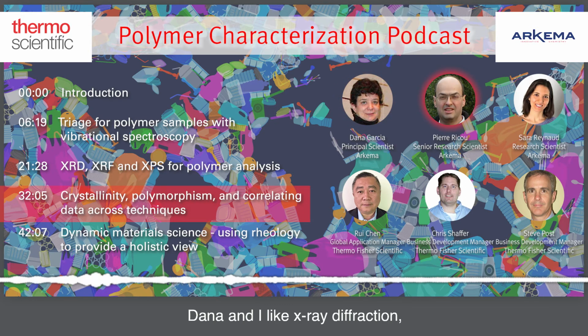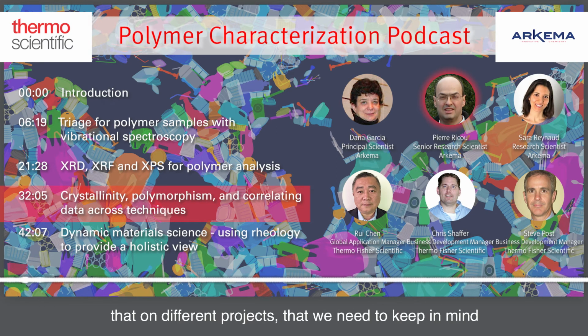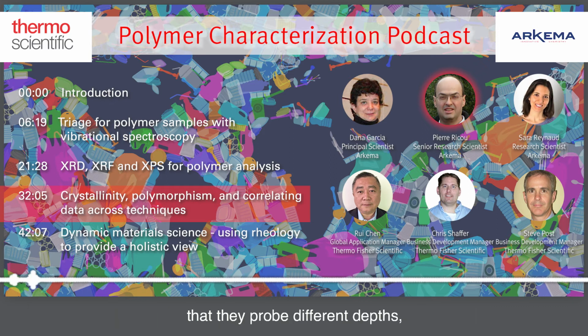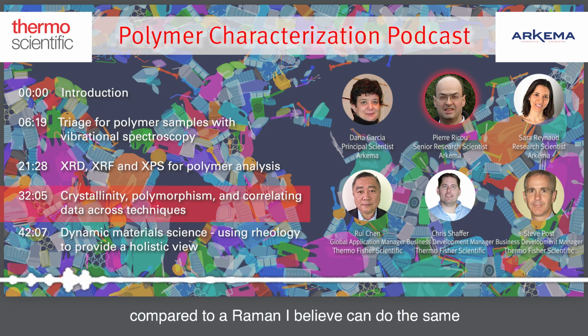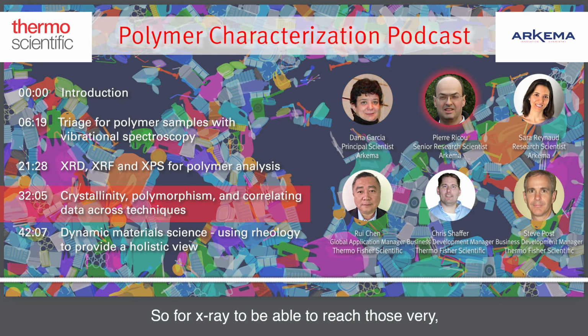I agree. I mean, Dana and I like X-ray diffraction, but I want to add that, when we compare techniques, and we are currently in the process of doing that on different projects, we need to keep in mind that they probe different depths, they probe different sizes, and that they're complementary. I mentioned very briefly that by XRD we can do micro diffraction. On a commercial lab instrument, you'll get down to about 100 micron in size. Compared to that, Raman, I believe, can do the same type of measurement at a 1 to 2 micron size. So for X-ray to reach those very small sizes, you're probably talking about a synchrotron beamline, which can be done, but it's not going to be done on a routine basis. So I see them to be complementary.